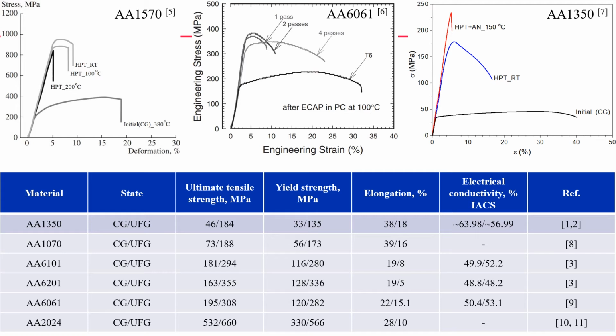Some results of applying the SPD processing are presented here. Obviously, the strength of UFG alloys is much higher than in the coarse-grained state, while maintaining a high level of electrical conductivity. However, another problem becomes apparent. SPD structuring leads not only to an increase in strength, but also strongly reduces the ductility of UFG materials, which greatly limits the scope of their functional application.